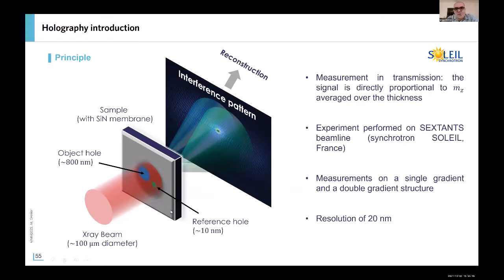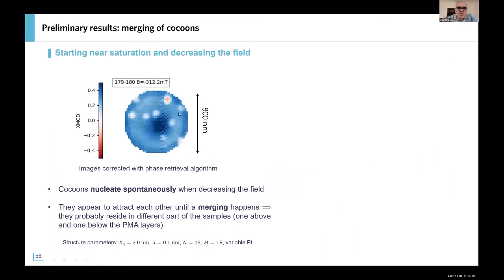But we used recently, in collaboration with Nicolas Jaouen and also Félix Büttner, a measurement at Soleil, this X-ray holography technique, where we use a coherent X-ray beam shone onto an object, but also at the same time a reference hole, and we can collect on the camera the interferences, the hologram, from which we can reconstruct the magnetic configuration with a resolution of about 20 nanometers. And this is a movie of what can be obtained by varying the perpendicular field.